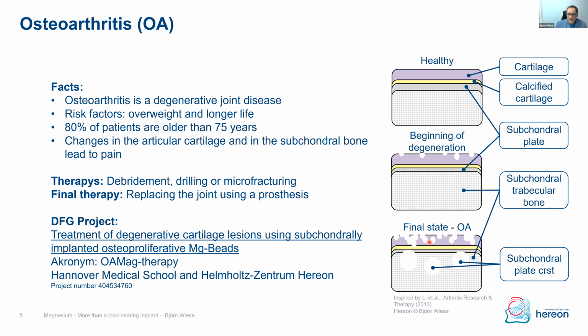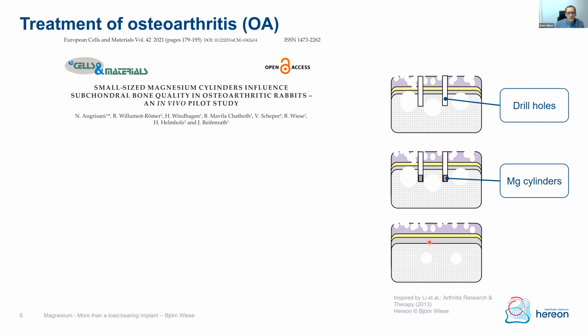At the same time, we started the idea to apply for a project, and we started together with the Medical School of Hanover a DFG project, and it got granted, on the treatment of degenerative cartilage lesions using subchondral implanted osteoproliferative magnesium beads, small pieces of magnesium. The first result, which we published quite recently, some weeks ago, it went online, is on an osteoarthritic model of a rabbit. And we're implanting inside this osteoarthritic knee, with the help of a drilled hole, some magnesium cylinders. The idea is to compare just the drilled group to the group with the implanted magnesium cylinders and see the effect later on the cartilage and the bone quality.